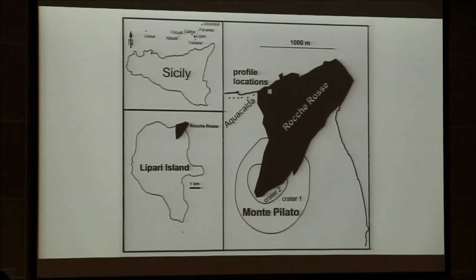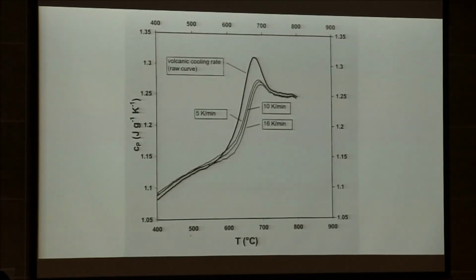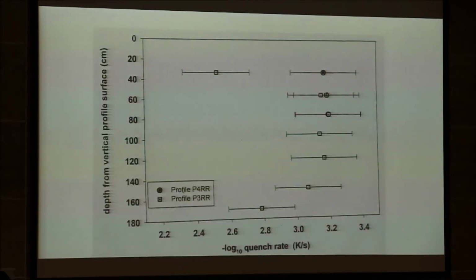We went to Rocche Rosse, which is a beautiful black glassy lava flow on Lipari. We got beautiful data for beautiful glass. This is the raw data right here. As usual, it cooled more slowly than our calorimeter. It's higher than our calorimeter. Then we calibrate it back and forth, back and forth at these rates, and we estimate a cooling rate based upon extrapolation to that value.